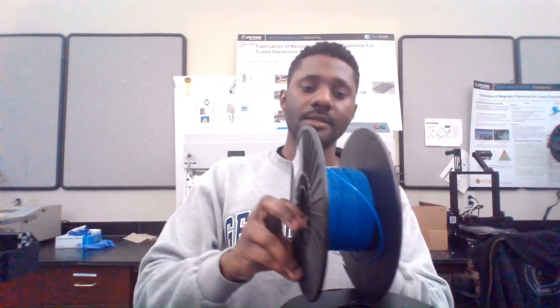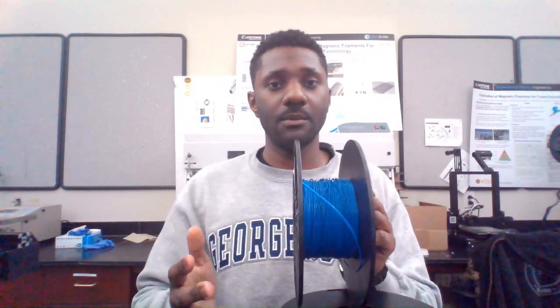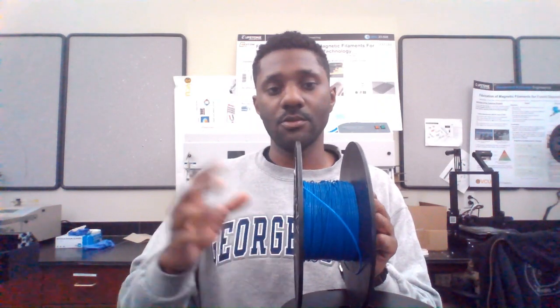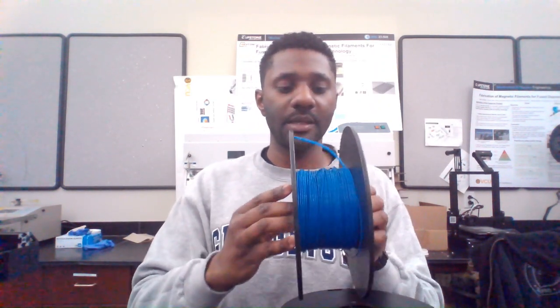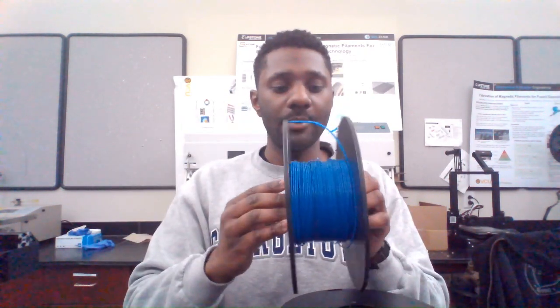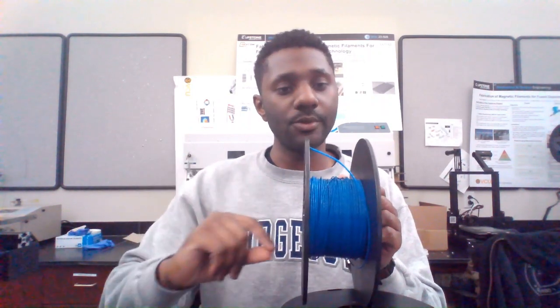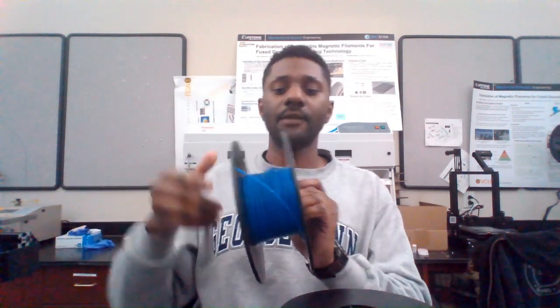And then we began to settle on 4% mix by weight, so 4 grams of blue colored pellets to 100 grams of clear raw PLA. With 4% mix, we were able to get a lot smoother color saturation throughout our spool. We were also able to get concrete and consistent readings from our diameter sensor, and a lot better pliability and flexibility within our filament. With the 4% mix, we have experimented with spools of filament that are within the acceptable diameter tolerances of about plus or minus 5%. This is used to test the integrity and printability of the filament produced by our extruder.